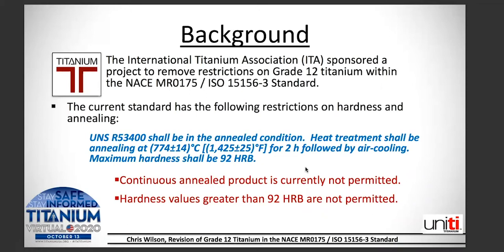The current standard has the following restrictions on hardness and annealing. UNS R53400, which is grade 12, shall be in the annealed condition. Heat treatment shall be annealing at 774 degrees C for 2 hours, followed by air cooling. Maximum hardness shall be 92 HRB.